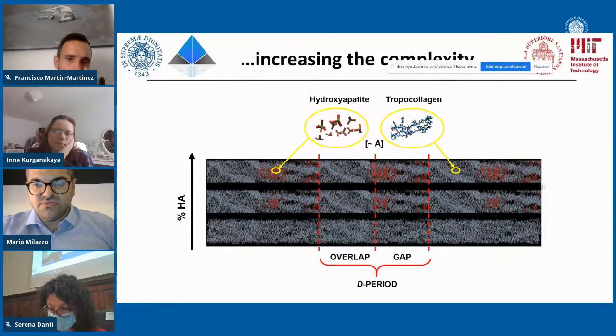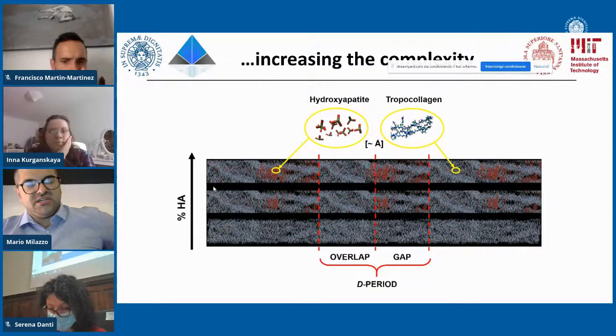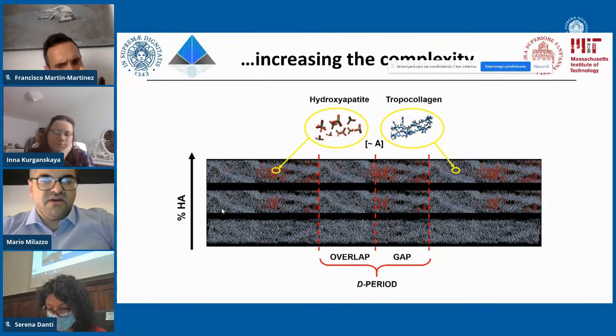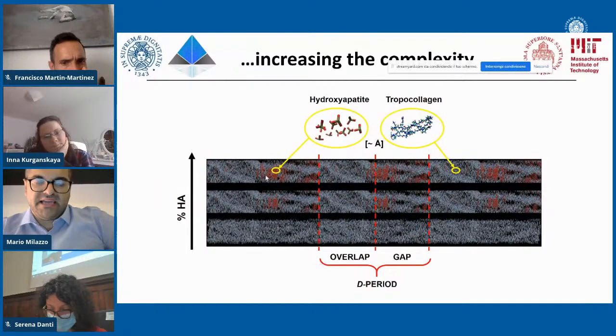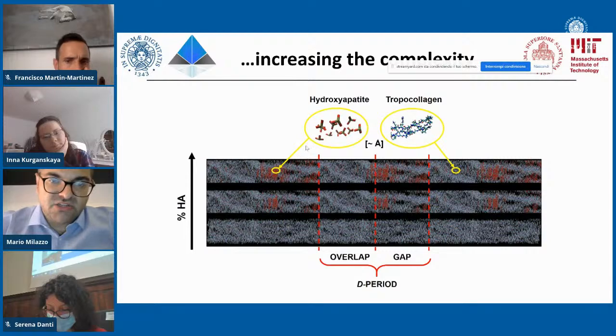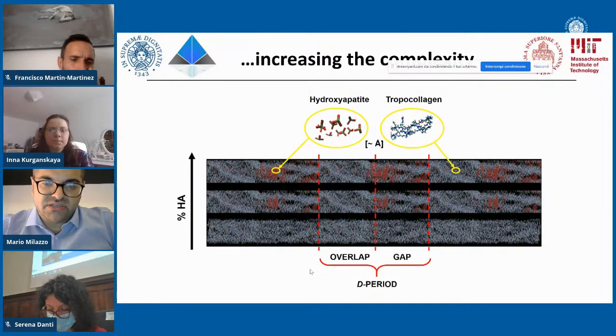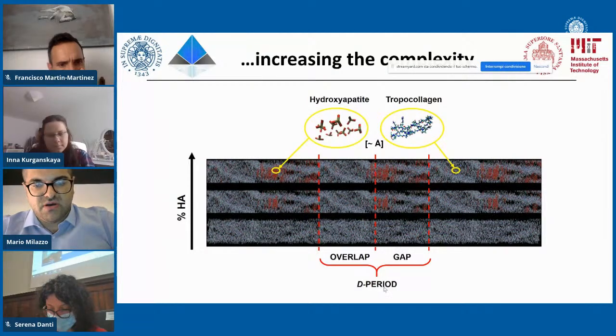And the other two features, the one in the middle is collagen fibrils with 20% of hydroxyapatite, and the last one is 40% hydroxyapatite. These are the three topologies that I studied in order to understand how waves propagate inside this kind of structure. In order to simplify my model, of course, I used only this section for the three topologies. So I studied only the D period composed by the overlap and the gap region.